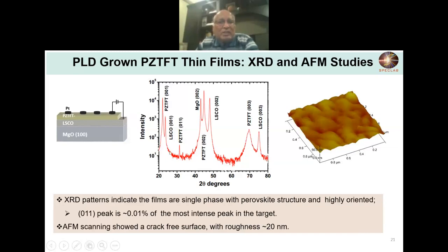We got excellent XRD spectra here. And you can see the films all look like they are oriented along 001, 002. There is a very small component of 011 here, which is something like 0.01% of the strongest peak. So there is a little bit of leakage of different orientation, but predominantly I would say the films were indeed very much textured.